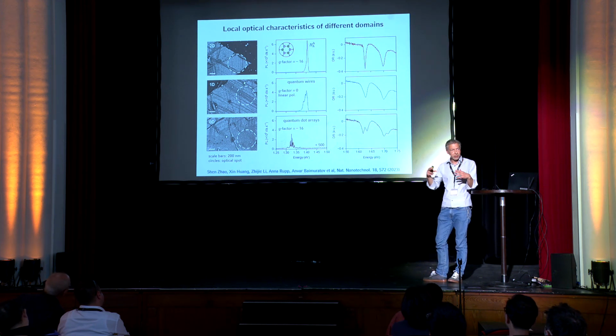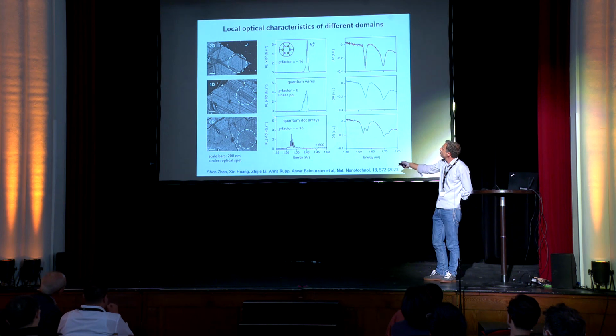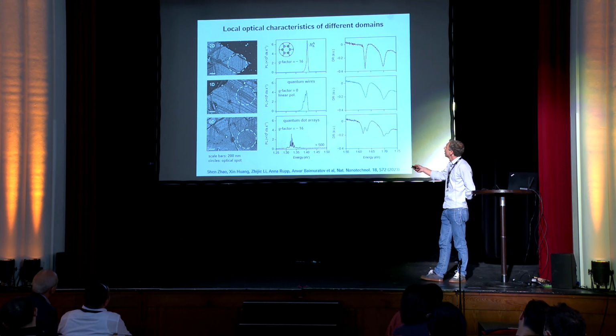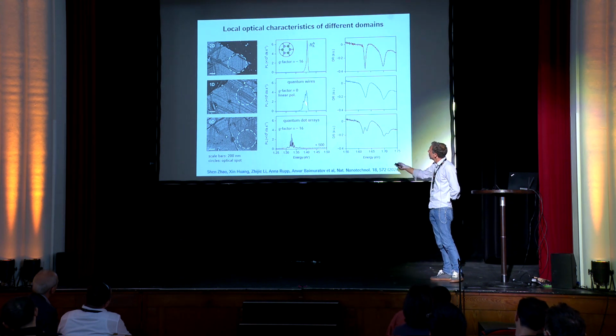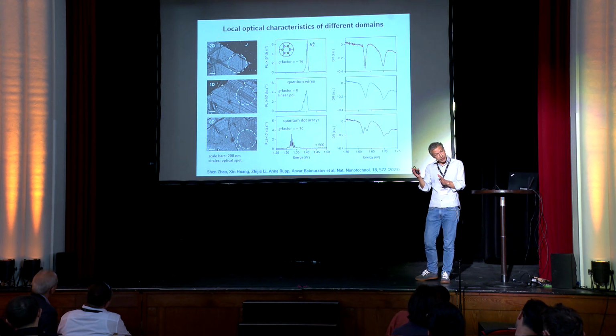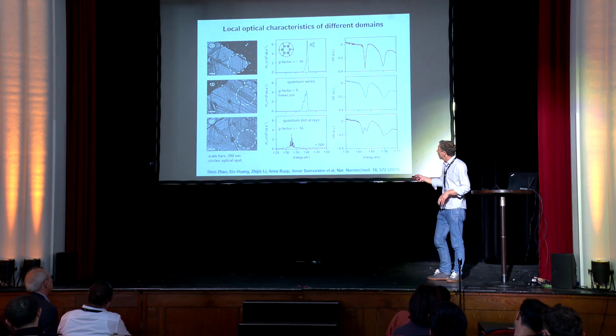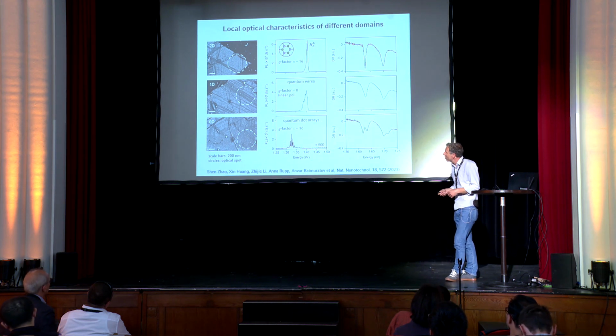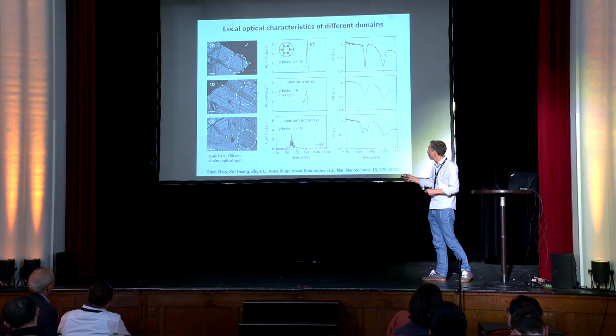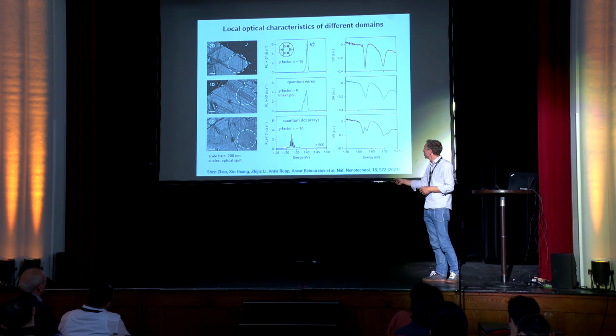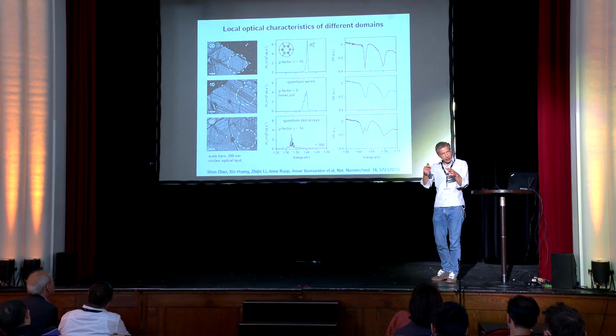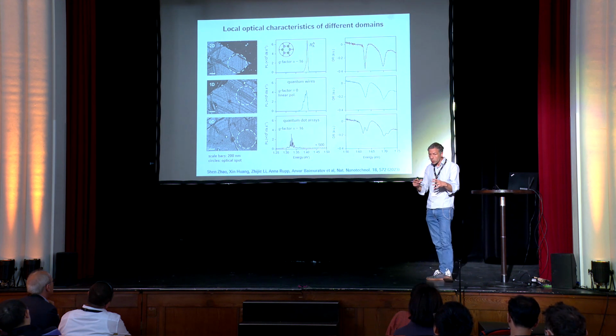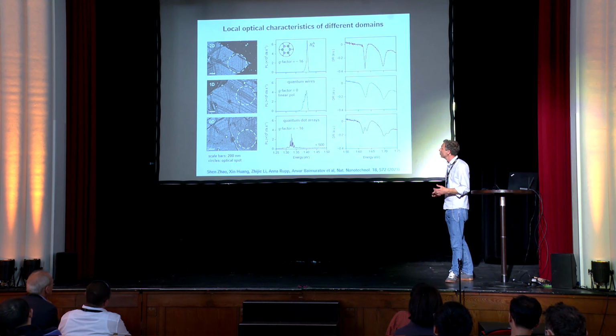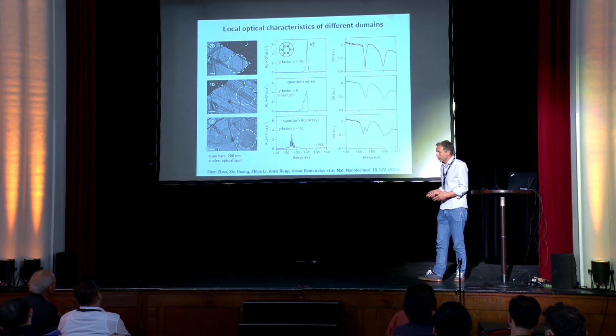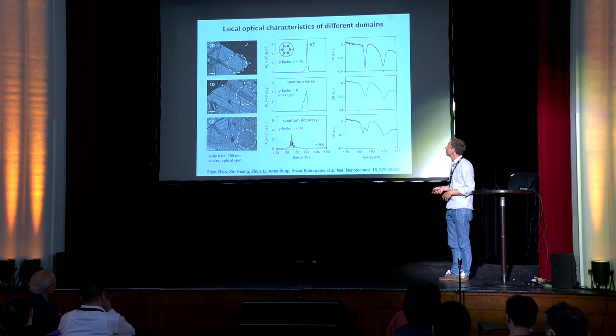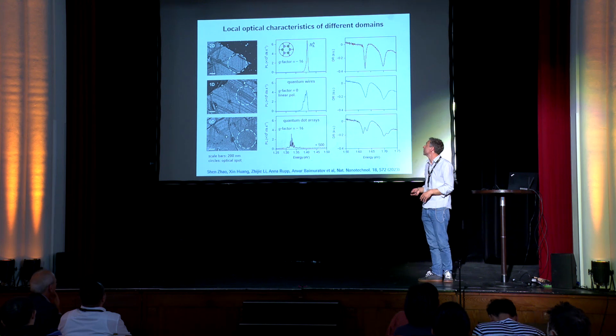Yet, as we move away from domains of one registry, for example, into the region where we find what we would call quantum wires, we find that the G-factor vanishes completely, and the photoluminescence emission would be linearly polarized, and the orientation of the polarization would be collinear with the wires. Then there are regions of quasi-zero dimensional domain network, what we would call quantum dot arrays. There we recover the G-factor of excitons, but see also the line multiplicity, reflecting the difference in the quantum confinement of these quantum boxes that have reconstructed non-ideally, non-periodically. And in absorption, one can basically trace these regions and make the same conclusions without going into the details here.